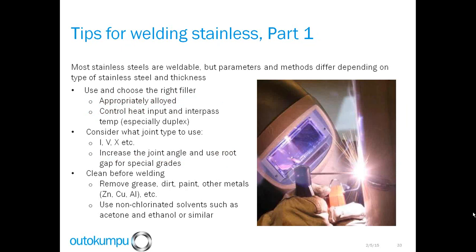Some more tips for welding stainless steel in general. And this goes for not only duplex but other grades, austenitic grades, special grades. You want to use the right filler metal, as I mentioned earlier. It's got to be appropriately alloyed for that grade. In all stainless steel welding, you've got to control the heat input as well as interpass temperatures. The right joint type has to be made, whether it's a V-type joint or an X double joint. Those are all considerations, and they really depend on the thickness of the material. We're going to have to increase the joint angle and the root gap when we're welding special grades as well as duplex stainless steels. And with any stainless steel welding, it's very important to clean before welding. Typically, you want to use something like acetone or ethanol that's going to clean the surface and then quickly evaporate so we don't have any weld contamination.